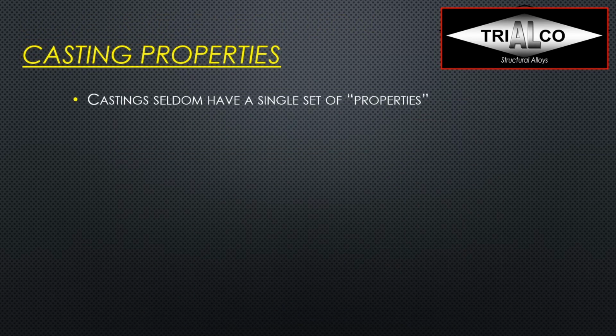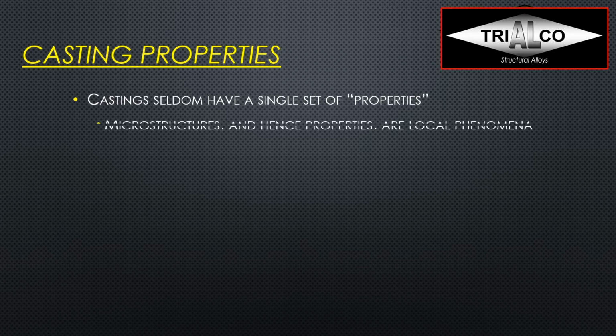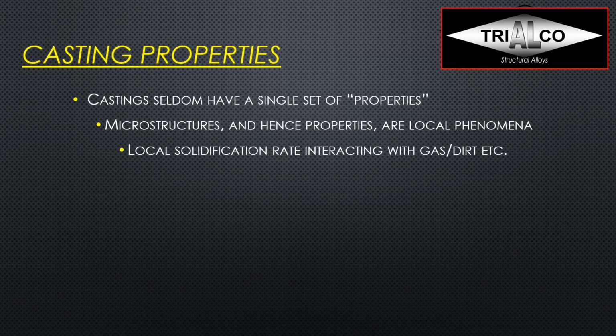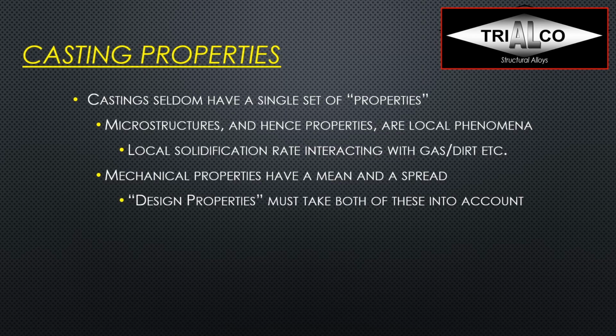So when we look at casting properties, we see that castings very seldom, actually almost never, have one single set of properties. The properties depend on the microstructures, and therefore they are a very local phenomenon. Local solidification rate is interacting with gas, dirt inclusions and all the things like that. So mechanical properties usually have a mean and a certain variation, a certain spread in the casting. So we need design properties, and they must take both of those into account.